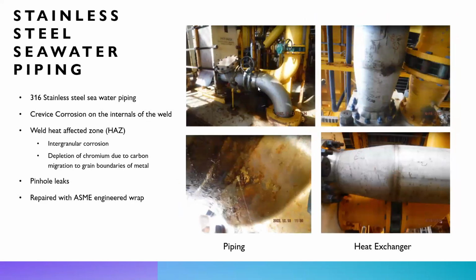Another stainless steel, offshore, we see that they use a lot of seawater for cooling water, and you see that in a lot of plants, anywhere from a power plant to a petrochemical plant. If you're next to the seawater, it's a good source of cooling water. You have a source of cooling water, but then you also have a source of corrosion. So in this case, they were having some corrosion at the weld.